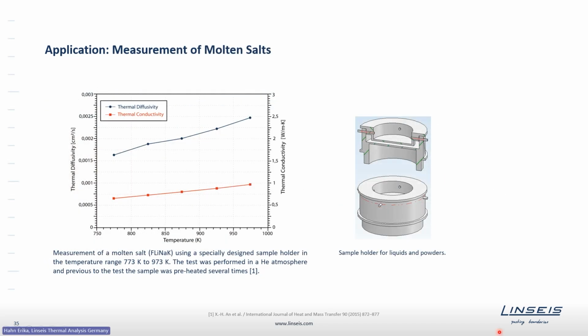Here's also a special application of a phase change material. Here we have an application of a molten salt. At room temperature, the salt is solid, but gets liquid at higher temperatures. And here a test was performed from 773 Kelvin to 973 Kelvin, where the thermal diffusivity was measured. The diffusivity was tested in the liquid state, where this special sample holder for liquids was used for the investigation.